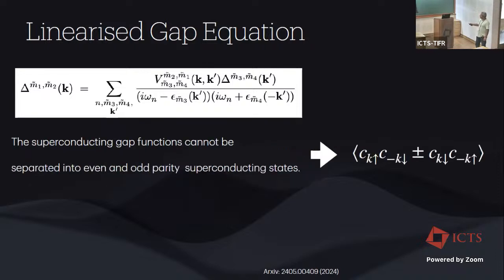Now, you also notice very quickly that the superconducting pairing that you have out here is of the form C_k spin up, C_minus k spin down. I'm, for simplicity, not putting in the band indices out here. But this does not allow you to write down the gap function in effectively a singlet or a triplet form. The reason is that if you consider a singlet with a minus sign out here, for C_k up you need a C_k down. But since for a given band, if you have a k up, for the same k you do not have a k down, right? They are spin-momentum locked states. So effectively, the system doesn't allow you to write or decompose the channels in terms of singlet or triplet. You have to look at this expectation value and extract effective singlet or triplet physics from it.